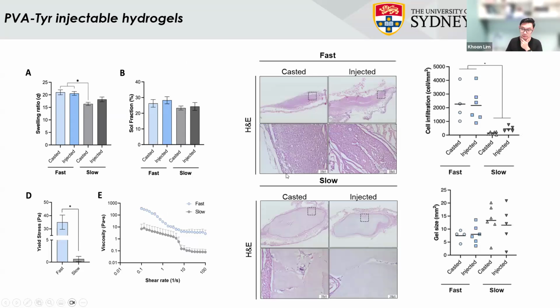When we implanted this subcutaneously, we didn't really see any differences in the hydrogel properties on how they interact with the surrounding tissue. So a cast gel and an injected gel, they really look similar. The degree of cell infiltration are the same, depending on the format. But what is different is if the gel is degrading faster, you get more cell interaction or cell infiltration. If it's degrading slower, you have less. And that's understandable. As the gels are degrading, they're opening up more space. And of course, more cells are able to get into the pocket of where the hydrogels are. So this is what we saw.